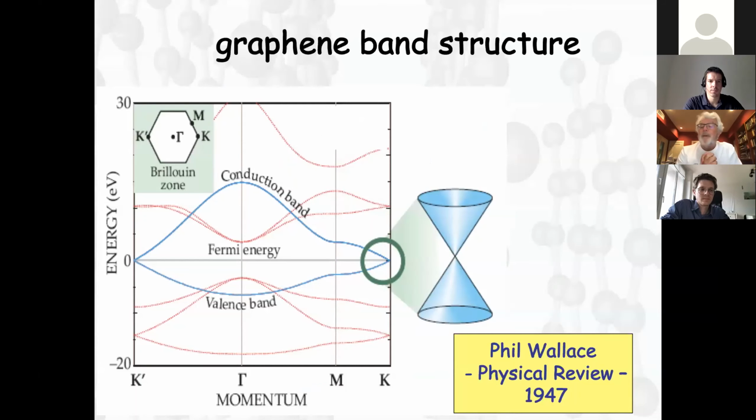So in my remaining time, I'm going to talk about twisted bilayer graphene. I think I have a little less, maybe 15 minutes or so. And so graphene is, first of all, bilayer. We're interested in bilayer graphene moirés. Many of you probably know that graphene at low energies consists of carbon pi orbitals on the honeycomb lattice, in blue in this more detailed band structure plot. There are 2 bands in a honeycomb lattice because a honeycomb lattice is a non-Bravais lattice with 2 atoms per unit cell.